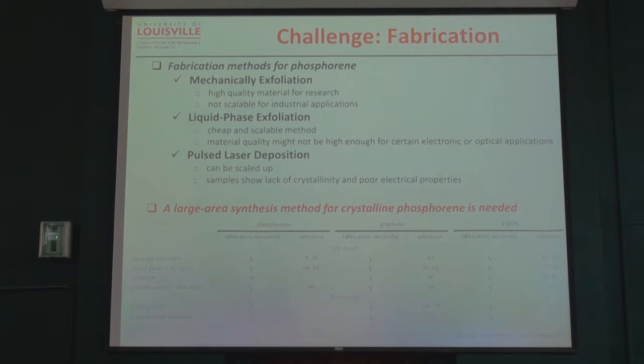So now, challenges of making phosphorene. We know phosphorene you can also make by something called mechanical exfoliation. That's how Manchester first discovered graphene, right? You take the bulk material, put the scotch tape and remove it and keep peeling it off until you get one layer. You can do the same thing for phosphorene, because that's a layered structure. Use the scotch tape, remove many layers, then do it again and again, like 100 times until you end up with one layer. That's what we call mechanical exfoliation.